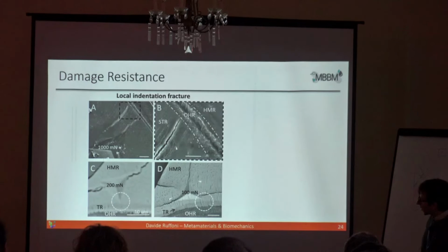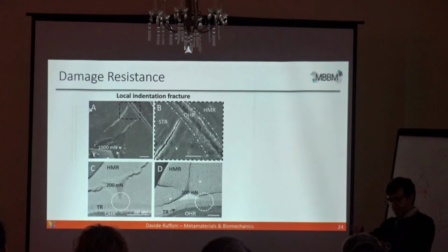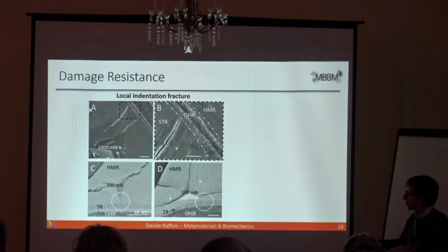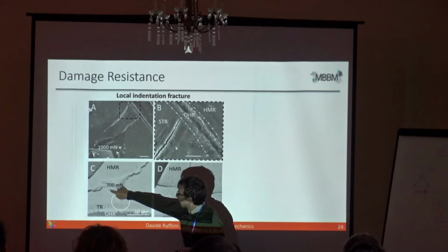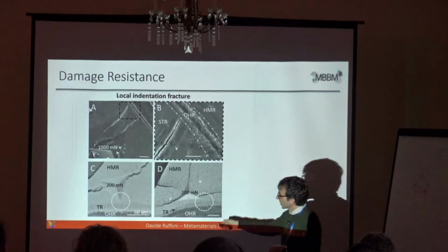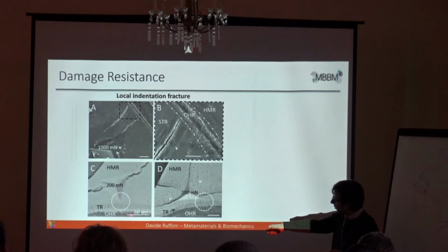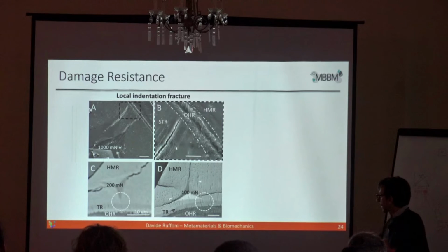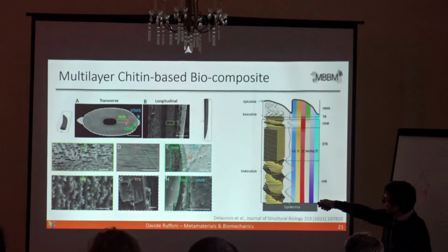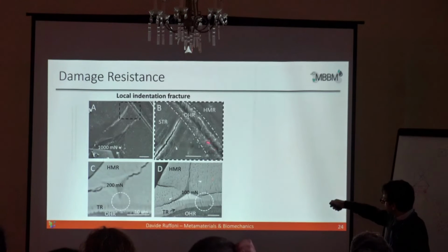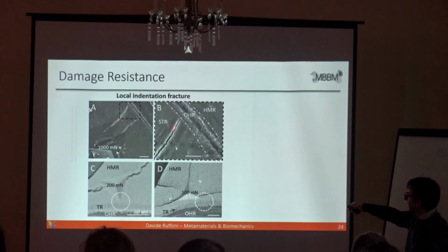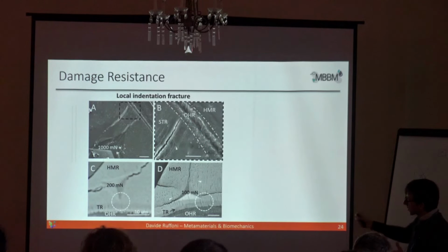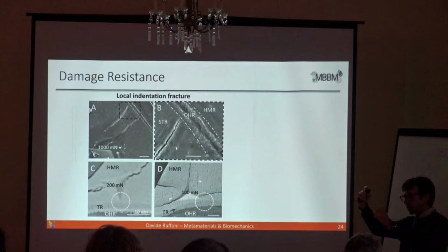And then what we also did was an indentation-based fracture study. So the idea is to fracture the tissue locally with high load indentation and to observe the cracks with electron microscopy. And what you see is that this is the indent fingerprint, and these are cracks, and this is the highly mineralized region, and the cracks are mainly propagating in the highly mineralized region, but they are not able to cross the interface where we observe this drop in mechanical properties. So all the cracks that we generated do not propagate through the interface. And also here, these are cracks which are generated inside the tissue. When they are generated here, they tend to go towards the outside, but they are stopped by these thin, less mineralized and more compliant layers. So we assume that one of the functions of this layer is to avoid cracks propagating between the 2 adjacent layers.